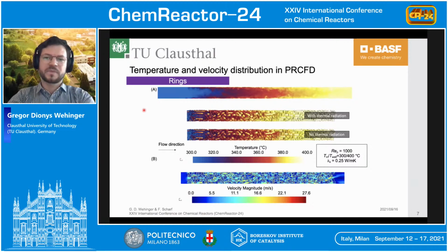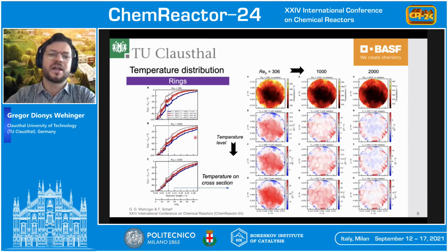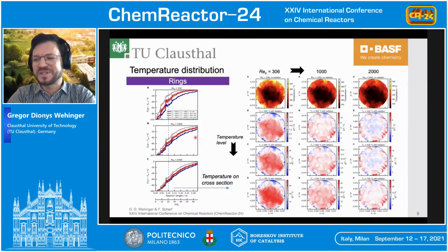So the thermal radiation effect, as I said, depends obviously on the temperature level as well as on the area that is irradiated by this hot reactor wall, as well as on the Reynolds number. So depending on these 3 aspects, we see different influences. And the particle shape and the Reynolds number obviously play an important role for lateral mixing, which also influences that. And for the rings, as you can see here, once again, the influence is not that strong. It might also be that the overall porosity in the bed of rings is much larger than for the spheres.